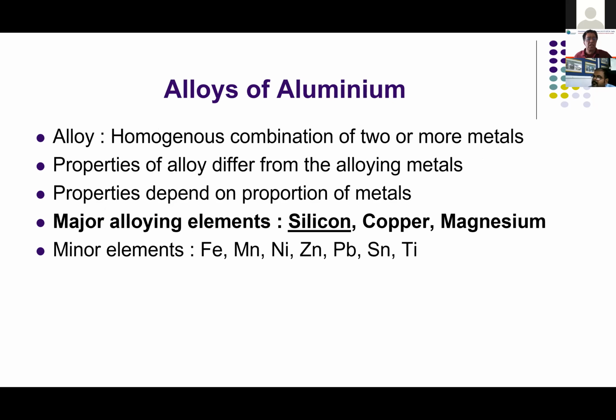Coming back here, if you see the minor elements, we mentioned iron, manganese, nickel, zinc. We discussed zinc. We discussed lead also. Tin. Tin is a funny material. This comes into the alloy. It is not supposed to be present, right? It comes into the alloy from the alloy maker. He collects all sorts of scrap from the market, puts it in the furnace and melts it to get this metal. Sometimes tin comes into aluminum scrap and gets dissolved.